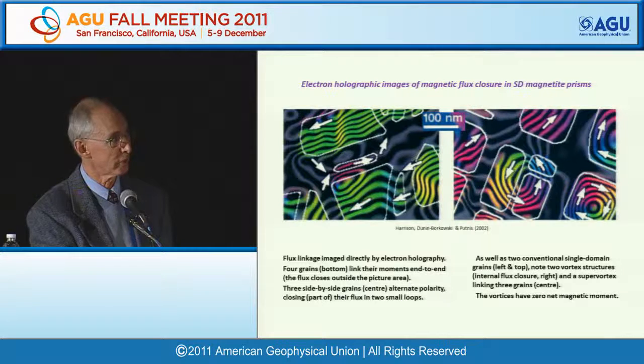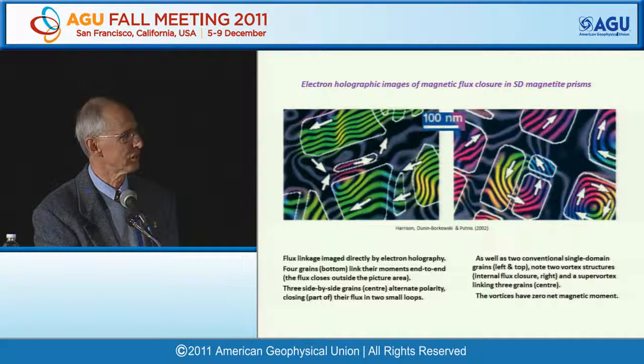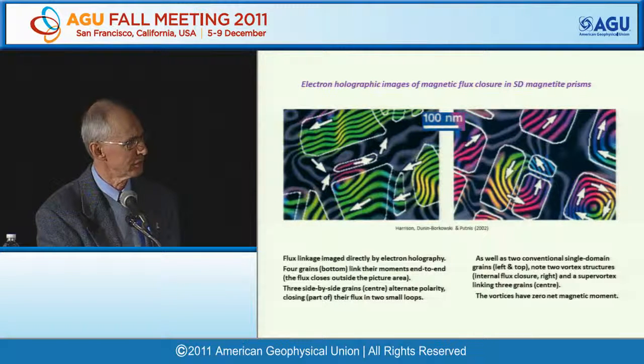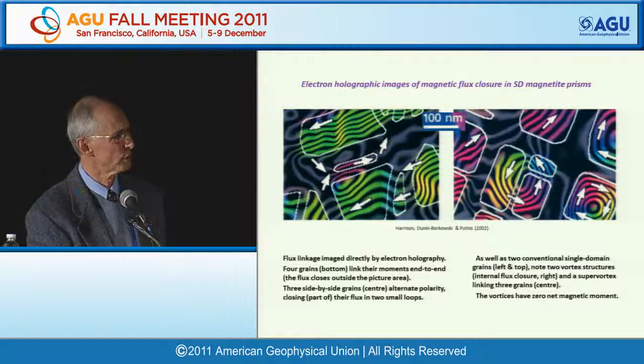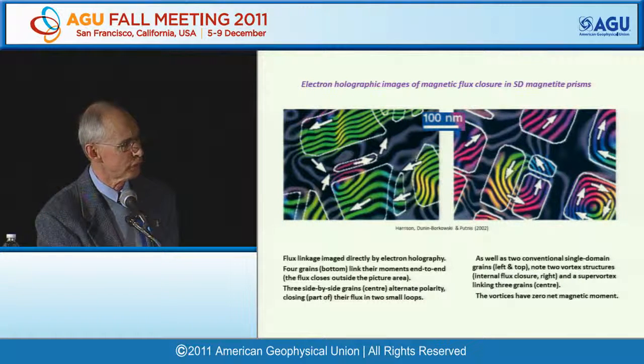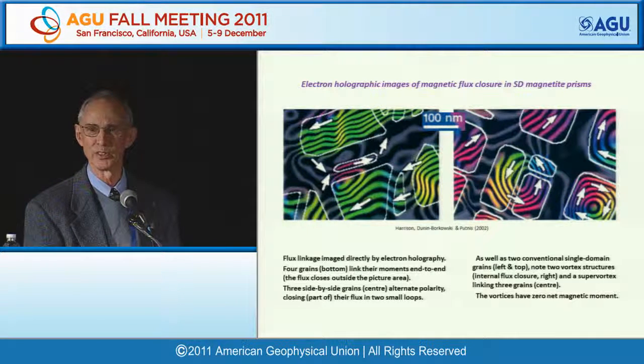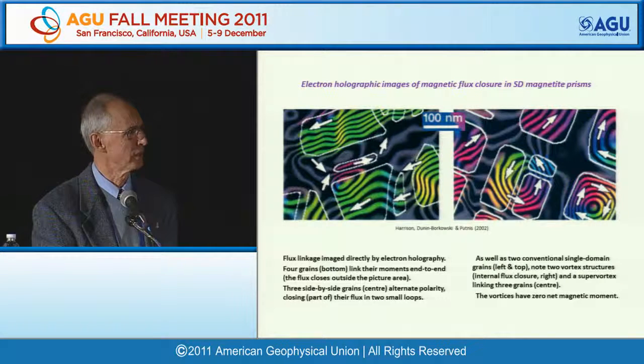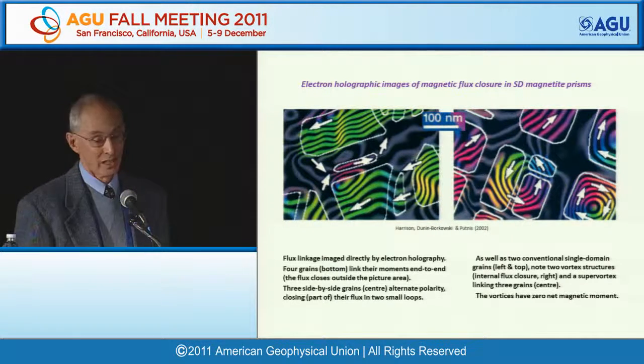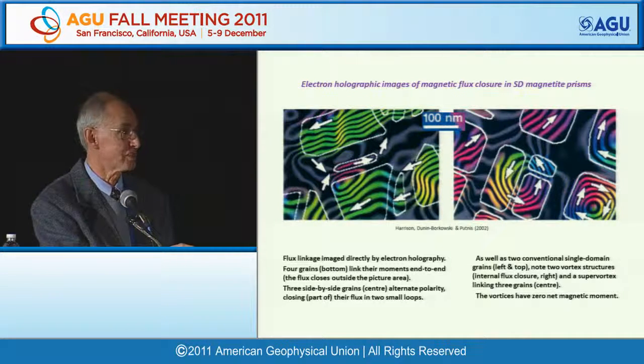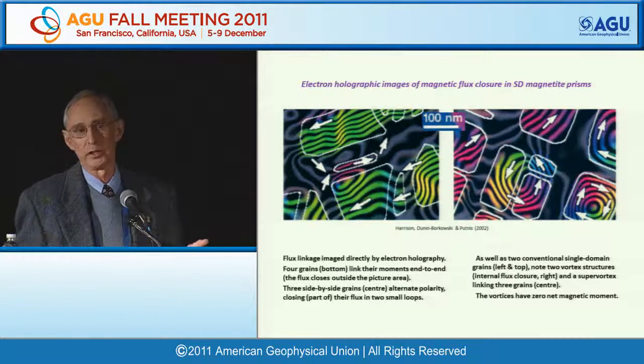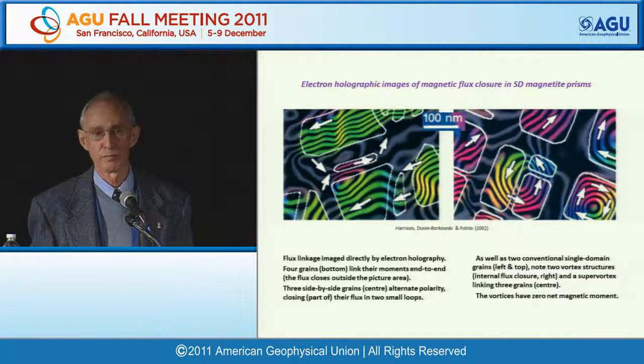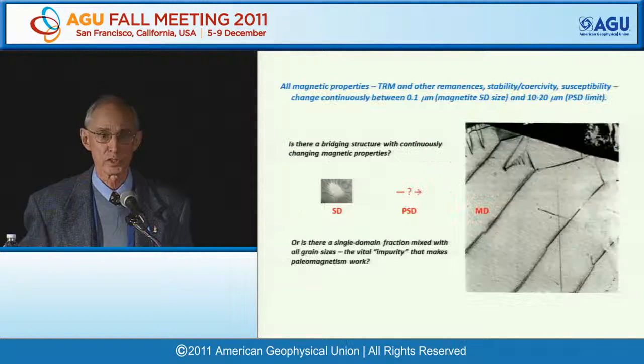On the right-hand side, notice the scale bar right on the single-domain size for magnetite. Here are some classic single-domain particles with flux lines continuing uniformly through the particle, and then on the right-hand edge, 2 vortex structures with internal flux closure, and an even more amazing thing to discover, what I call a supervortex, which links together these 3 neighboring particles. So it has it both ways, compass needles lined up end to end and side by side. Well, the bad news, of course, is that these vortices are not very good for paleomagnetism because they hardly have any magnetic moment. Very hard to produce a high-intensity TRM if you start with something with these small moments.